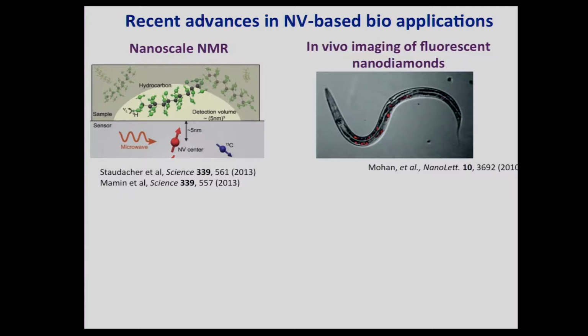A little bit earlier, there was a demonstration of injecting fluorescent nanodiamonds containing NV centers into worms, C. elegans. In this case, the worms were fed nanodiamond-containing food, or they were injected, and imaged for several days. The worms did just fine, and the NV fluorescence was maintained over many days. So this is an indication of the non-toxicity and the photostability of NV centers. These little red guys are the NV centers.